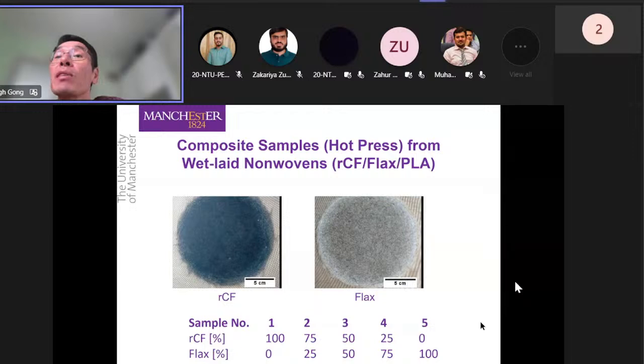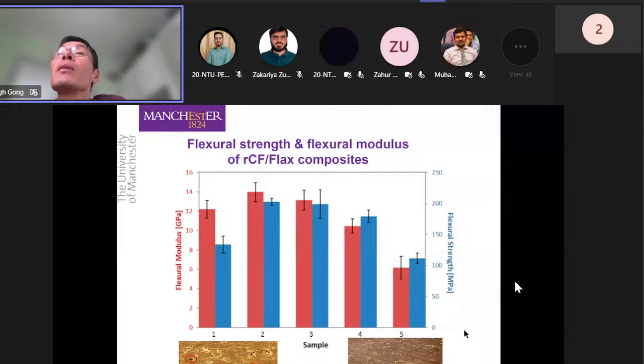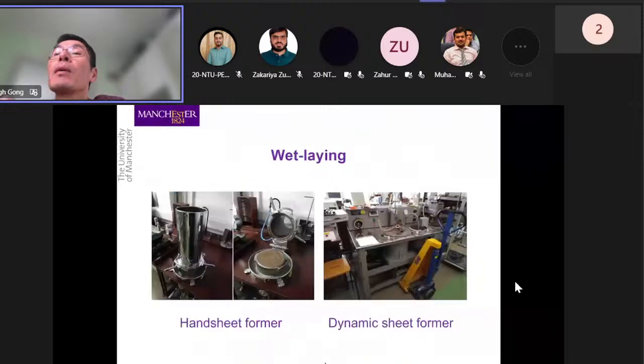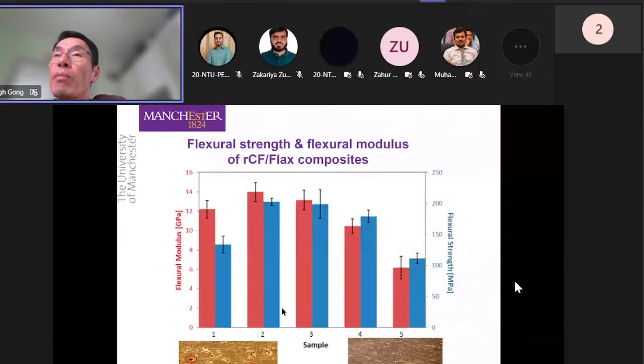So we mix the carbon fiber with flax fibers, because obviously carbon fibers are rigid, hard to disperse, while flax fibers are hydrophilic. It's easier to mix in water. So we tried, in this particular case, 5 different samples with different mixing ratios. And then you look at the composites made out of that, and you find actually, if I just go back to remind you what number 2 is, because that seemed to be the best performing, which you can see here, with 25% of flax fiber, we can get actually better performance compared with 100% carbon fiber. It's just because of the way the fibers disperse in the composite.